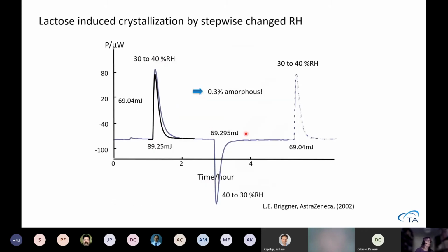A very sensitive method to look at the amorphous content is again to use the RH perfusion ampule, but then you step between certain relative humidities. You will equilibrate the whole thing at 30% relative humidity, and then you step up to 40%. So you get the peak absorption and maybe crystallization if you have an amorphous part. Then we can step down back to 30, we get desorption, and then we can step up again just to verify. If I now move this peak here, where I go from 30 to 40, we can see that they are not completely overlapping. So between 89 for the first peak and 69, that difference is related to the crystallization of the amorphous material.